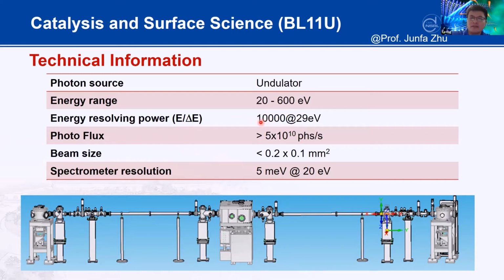It's about 10,000 at 29 eV. The flux can reach about 5 times 10^10 photons per second, and the beam size is much smaller compared to the bending magnet. The beam size is about 0.2 times 0.1 millimeter square, and it can be optimized further. The spectrometer resolution is about 5 meV at 20 eV.